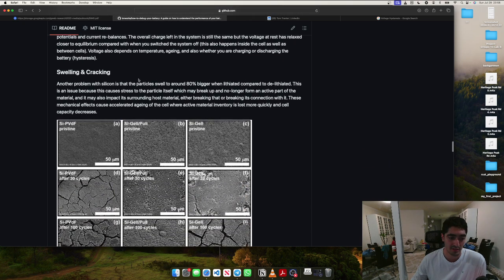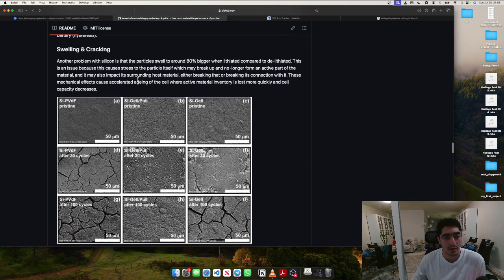Hysteresis, swelling and cracking. Another problem with silicon is that the particles swell to around 80% bigger when lithiated compared to when delithiated. This is an issue because this causes stress to the particle itself, which may break up and no longer form an active part of the material, and may also impact its surrounding host material, either breaking that or breaking its connection with it. These mechanical effects cause accelerated aging of the cell, where active material inventory is lost more quickly and cell capacity decreases.